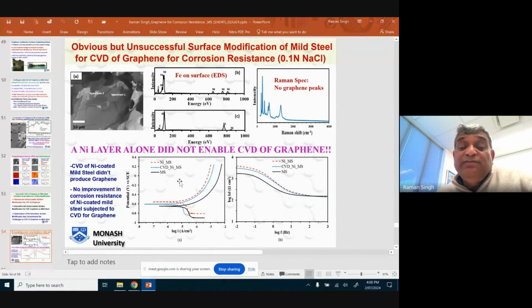It doesn't work for a very simple reason. Those who know metallurgy will know that iron too has very high solubility of carbon. So whatever carbon diffuses into nickel, it leaks into mild steel. So you have the mild steel substrate, and on top of that, you have the nickel coating. Yes, you will have splitting of hydrocarbon, and carbon diffusing into nickel, but that carbon will leak across the interface into the mild steel substrate. So that's where the problem was. That's why we could not develop graphene. Raman spectroscopy says no graphene and no improvement.